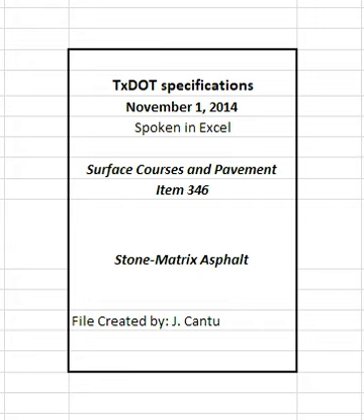4.4 Mixture design. 4.4.1 Design requirements. Use the SMA design procedure provided in Tex-204-F, unless otherwise shown on the plans. Design the mixture to meet the requirements listed in Tables 1, 2, 3, 4, 7, 8, and 9. Design SMA or SMAR mixtures using a Superpave gyratory compactor, SGC, at 50 gyrations as the design number of gyrations, N design. The N design level may be reduced to no less than 35 gyrations at the contractor's discretion.